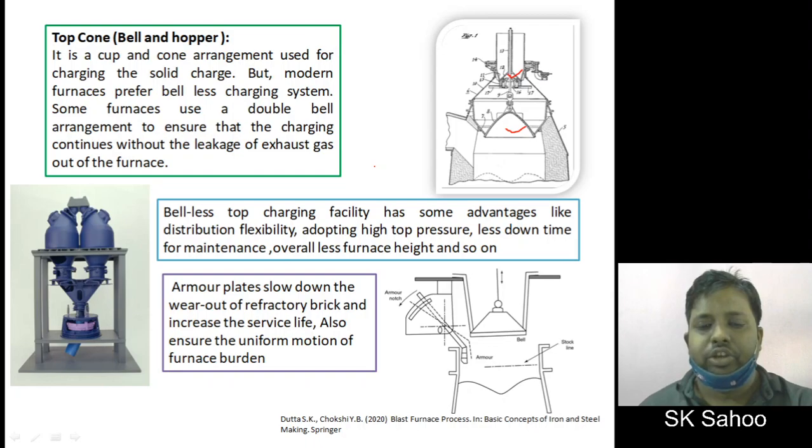But nowadays, most of the furnaces have a bell-less charging system. This type of charging system is being used because the bell-less top charging facility has some advantages like distribution flexibility and uniform distribution, ease of maintaining high top pressure, less downtime for maintenance, overall less furnace height, and so on.